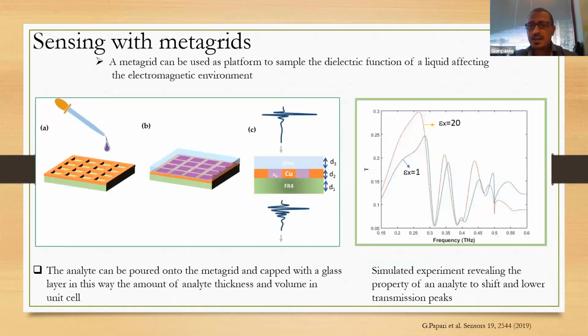Now, we have peaks. We want to use the metagrid to sense the dielectric properties of an unknown analyte. What can we do? We can take these metagrids, we can pour an analyte, and we can cover the structure, in this case with glass, because I have a layer of glass 150 or 160 micron in thickness that we have characterized in order to improve also the reliability of simulations.